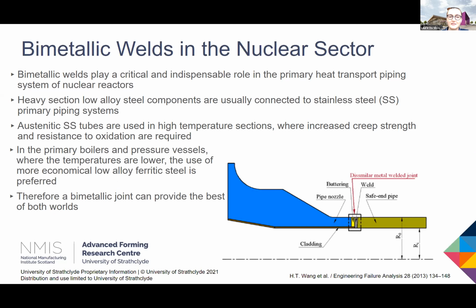So the austenitic stainless steel tubes illustrated in the green are used in high temperature sections where we need increased creep strength and a resistance to oxidation. Whereas in the primary boilers and the pressure vessels where the temperatures are lower, you can normally get away with using a more economical low alloy ferritic steel. So therefore the bimetallic joint can provide the best of both worlds in terms of properties for the application.